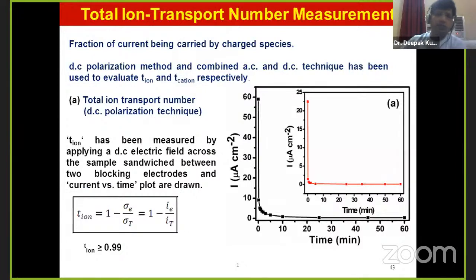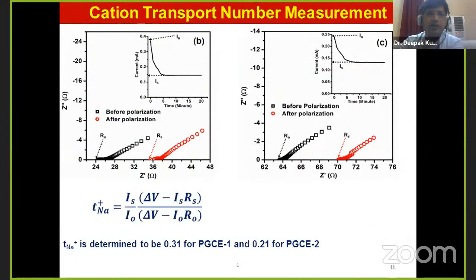The ion transport number, to know the percentage of the total ions which are flowing through the system, we have determined utilizing the DC polarization technique, and we have found that the conduction is 99% ionic. The cation transport number is also determined using the Bruce-Vincent method, and we found the cation transport number to be 0.3 for one system and 0.2 for the other system, and both are cocktail systems in which the concentration is different.